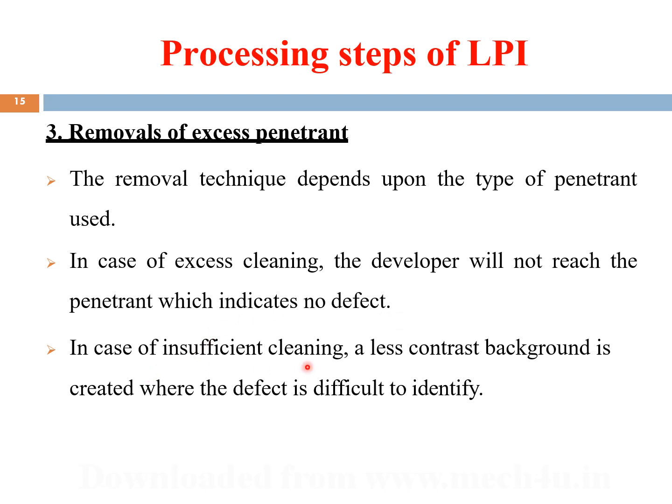Or if the cleaning is insufficient, that is, it is not properly cleaned, then there will be a contrast difference. When the inspector is viewing it under a certain light source, a low contrast background will be there, so the defect will be difficult to identify. We cannot identify the size of the defect, or where the defect is, because of the low contrast background. So the removal technique is very, very important. The removal of the excess penetrant depends on the type of penetrant used.